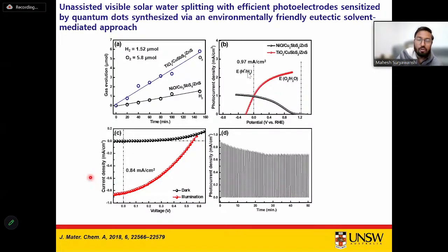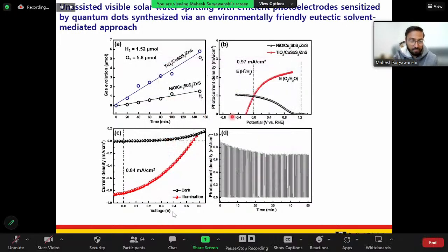So what does that mean? We have only prepared this two electrode system, and we shine the light on that particular system, and we were able to see the production of the hydrogen and oxygen on a photocathode and photoanode respectively, with a produced current density of about 0.9 milliampere per centimeter square, and the solar to hydrogen conversion efficiency about 0.23%, which was one of the highest recorded conversion efficiency for this kind of photoelectrode system that we achieved in 2018.